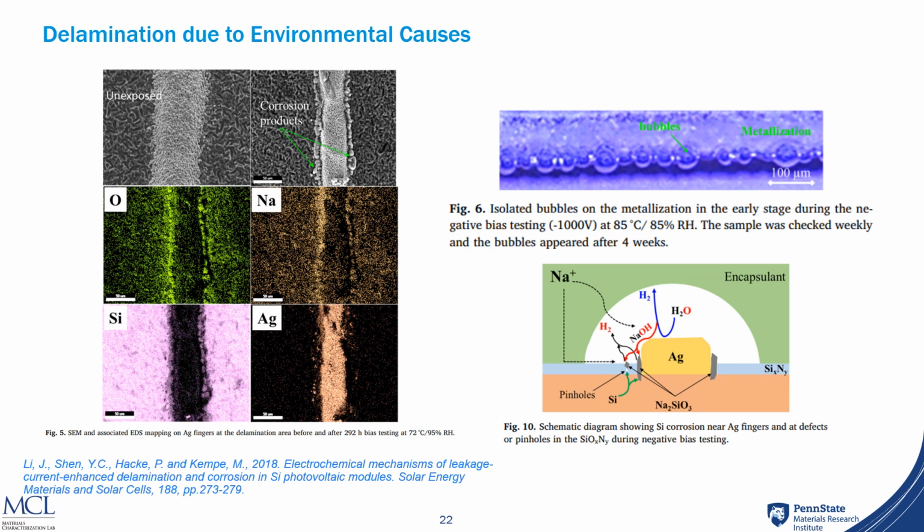As they examined the actual layers where there had been failure, they could see evolution of sodium and silver in these delamination zones. This is done through an SEM photo. And this is something I've actually seen before on a different type of material, a low E coating, where you get evolution of silver that is then exposed to an area where sodium is found, and you get a rapid reaction between the sodium and silicon, and that resolves off as gas.